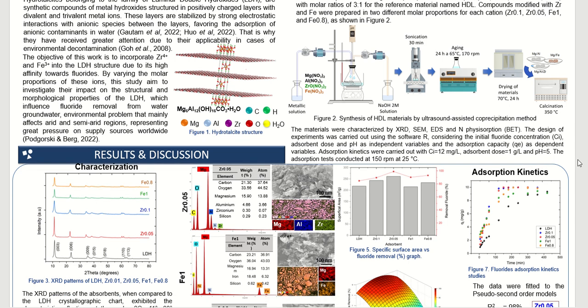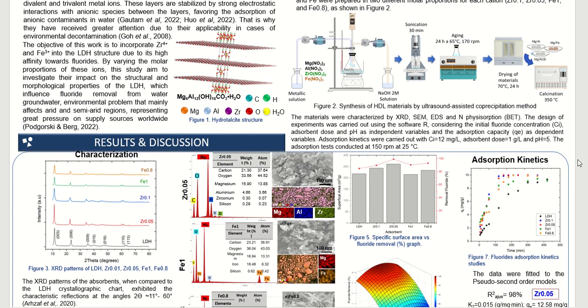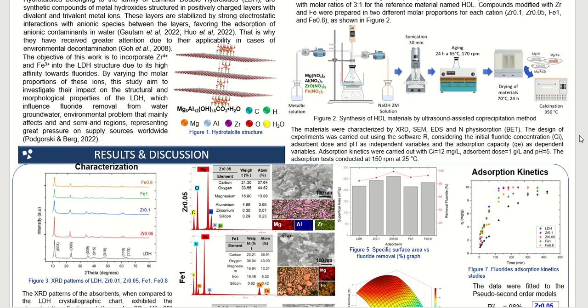Hydrotalcite is composed of magnesium and aluminum cations in the layers in a ratio of 3 to 1 molar respectively. Therefore, in the modification, it was proposed to integrate zirconium in molar ratios of 0.1 and 0.05 molar. And in the case of materials modified with iron, the ratios of 1 and 0.8 molar.